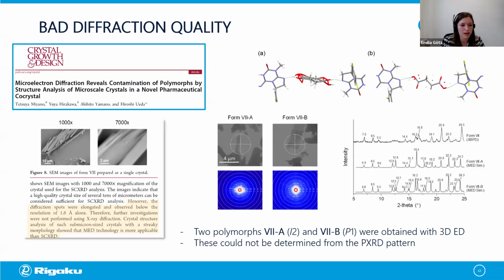And for this structure by Miyano et al., they actually tried single crystal X-ray measurements for a polymorph of this API, but the diffraction spots were elongated and the resolution was not sufficient. And the XRPD pattern did not indicate several phases, but they also weren't able to index it correctly. And after the 3D-ED measurements, they realized that the polymorph they were looking at was actually 2 different polymorphs, which you can see here. And their peaks in the powder pattern simply had a lot of overlap.